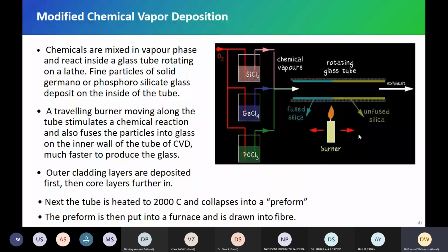Actually we may not need these bubblers. The bubblers are very popular, but sometimes we can also blow these materials with a blower. A lot of things are possible there. This is a standard design, but we can play with it and try to send chemicals. The idea is that SiCl4 should convert into SiO2. So it is better to have SiCl4 as very minute droplets, and oxygen; heat it, you get SiO2. You have GeCl4 minute particles, heat it, and you can get GeO2. So just pass these liquid particles through it, with sufficient oxygen so that they convert into oxide.